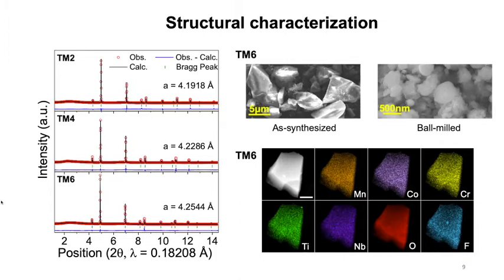And here is the XRD pattern of the 3 materials, and they all show an overall DRX structure without any observable impurity signals. And the particle size of the synthesized materials of all the 3 compounds is around 5 to 10 micrometers, and that can be reduced to around 200 to 500 nanometers after ball mill. And the EDS mapping of the TM6 as a representative shows that all the elements are distributed uniformly through the particle.